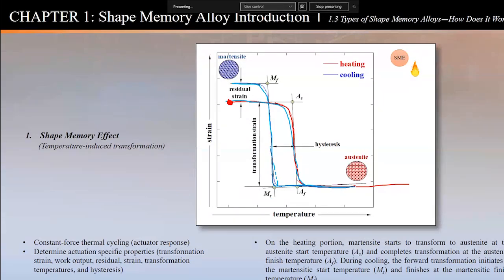Now a couple of things that you see here. This path here doesn't take the same path. This little gap in between is known as the hysteresis. This hysteresis can be anywhere from 10 to 100 degrees C, for example, depending on the alloy. This length here, when it heats, it shrunk by this much, is known as transformation strain, or the actuation that you expect from this material. How much is it going to expand?